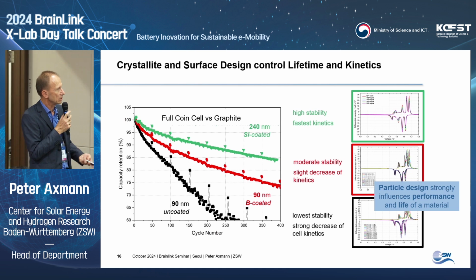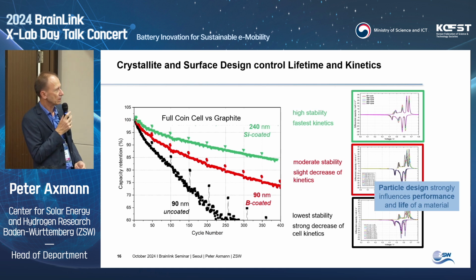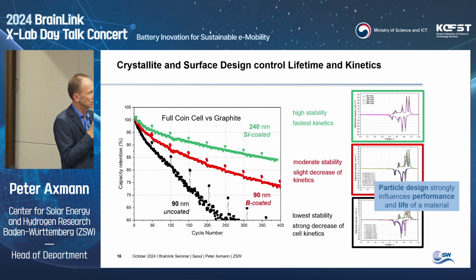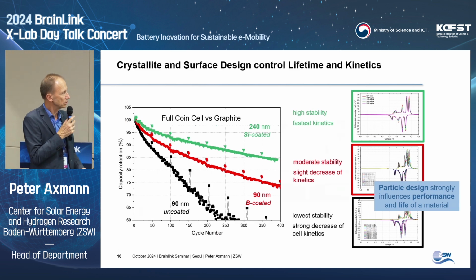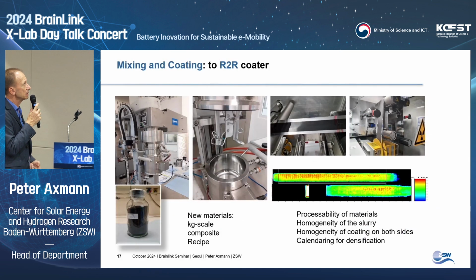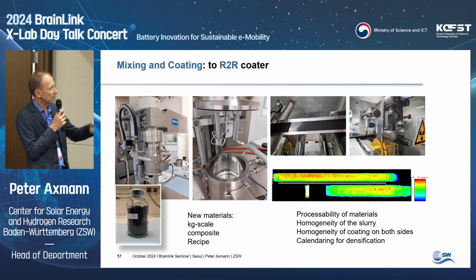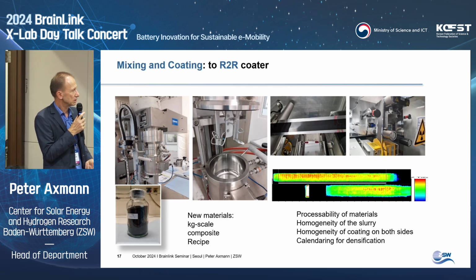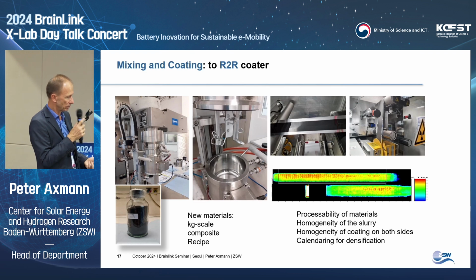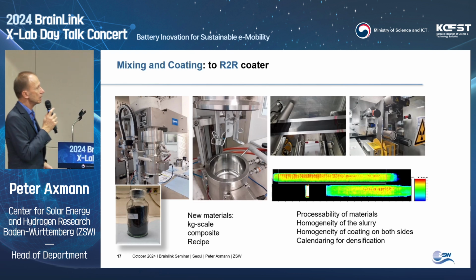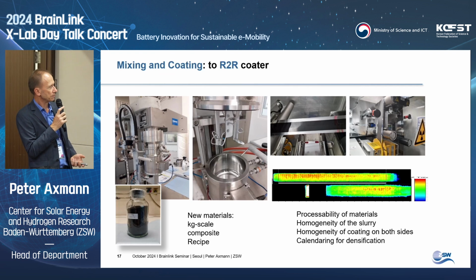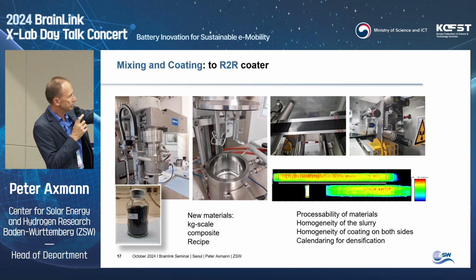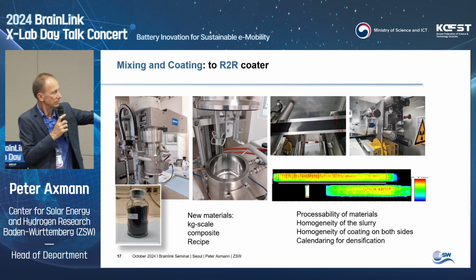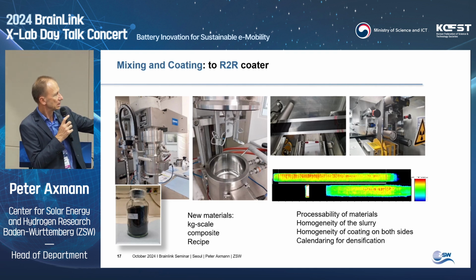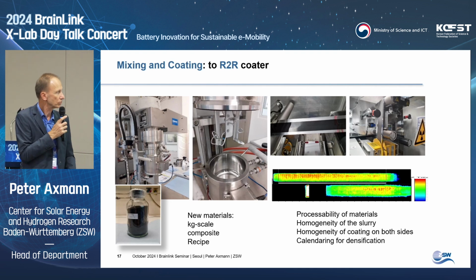So particle design strongly influences performance of the material itself and the life of the materials, but now we go a step further. What if we handle this material in the processing? Here we have to take the material, we have to mix it, we have to coat it, we have larger mixtures. If we take a new material on a kilogram scale, we have to develop recipes for that. And I would focus here, in the line of the mixing, the coating, and finally densification of the electrodes, just on the mixing and the densification, just to show the influence of particle morphology on both factors.